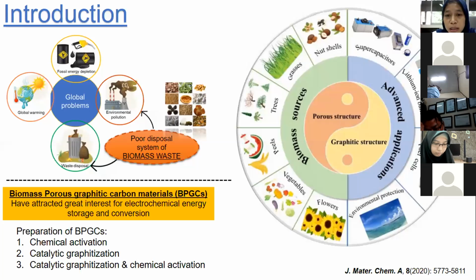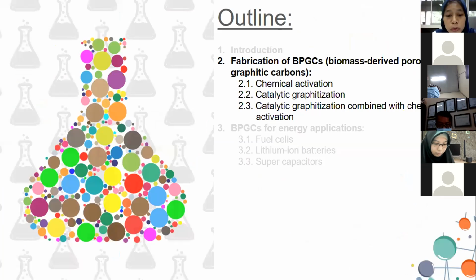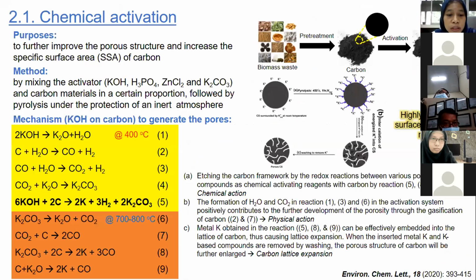And next, we go to fabrication of the biomass-derived porous graphitic carbon. First method is chemical activation. Chemical activation has the purpose to further improve the porous structure and increase the specific surface area of carbon. The chemical activation method is usually mixing the activator and biomass material in certain proportion, followed by slow pyrolysis under the protection of an inert atmosphere.